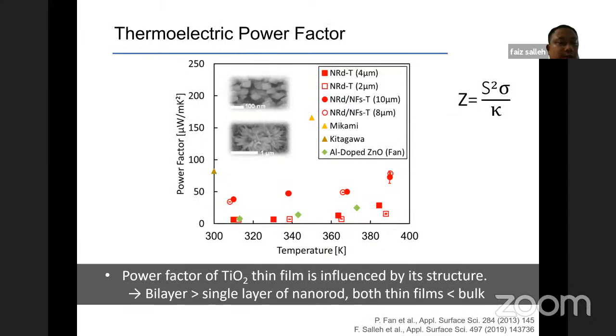Okay, next we look at the thermoelectric power factor. This graph shows the thermoelectric power factor as a function of temperature. We have measured two types of material. As I mentioned, we have the bilayer, which consists of nanorod and nanoflower, and we use this NRD and NFST. And one more, this square shape, the single layer, which consists only of the nanorod structure. We also varied the thickness. For example, the nanorod is around 4 micrometer, and we reduce it to around 2 micrometer. For the bilayer, we have 10 micrometer and 8 micrometer. We also plot in this graph the bulk TiO2, represented by this triangle, and the reported aluminium-doped zinc oxide, represented by this diamond.